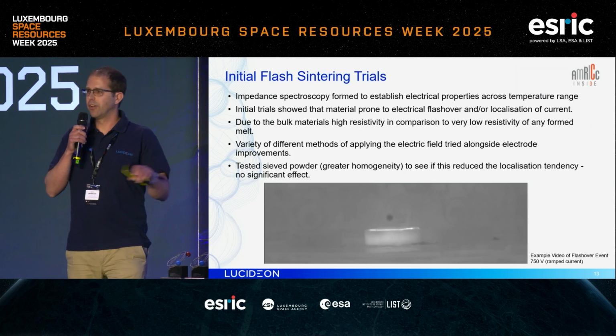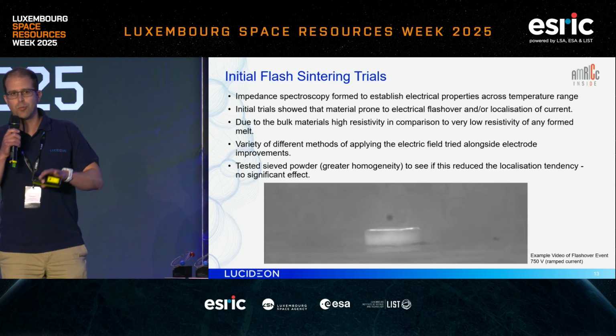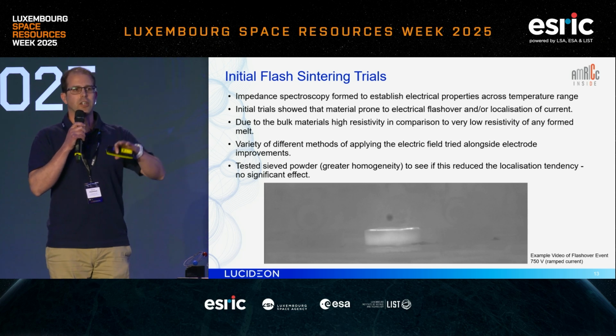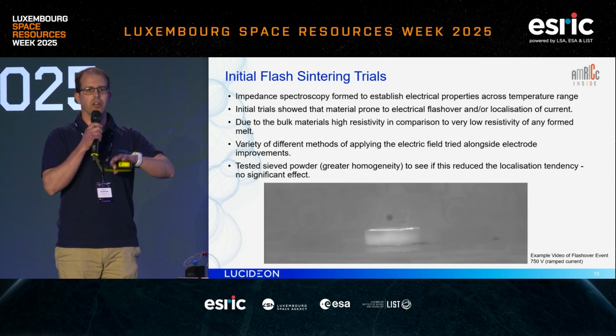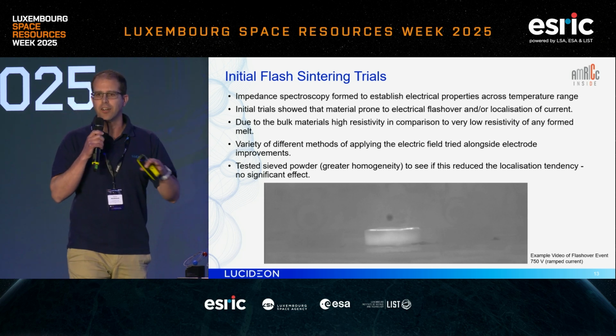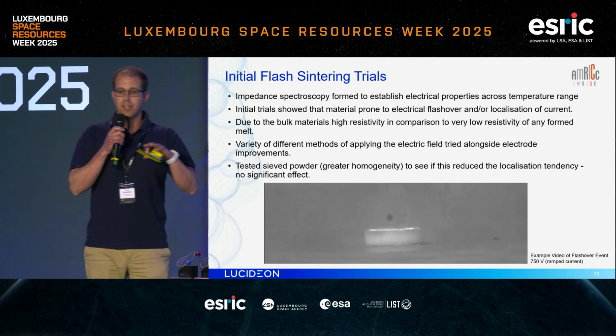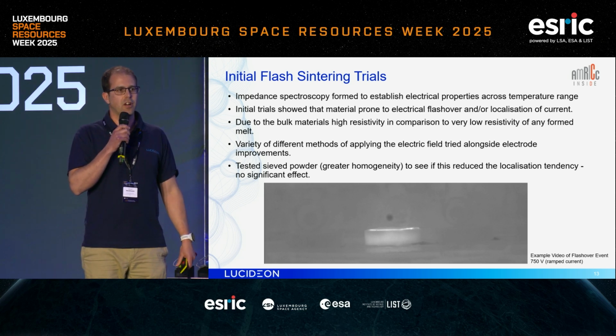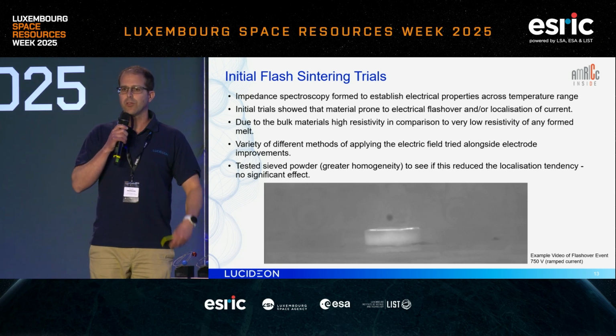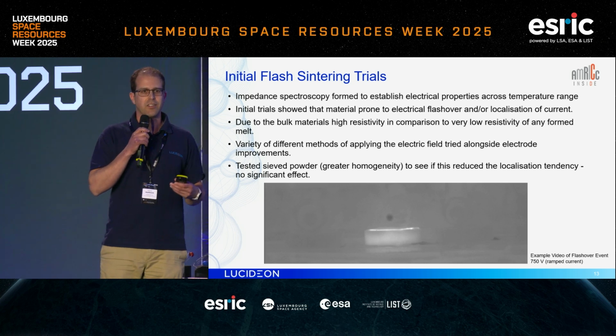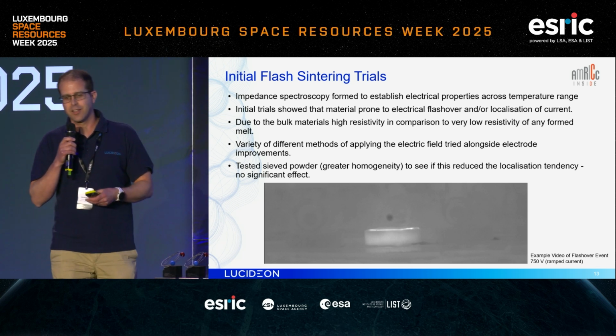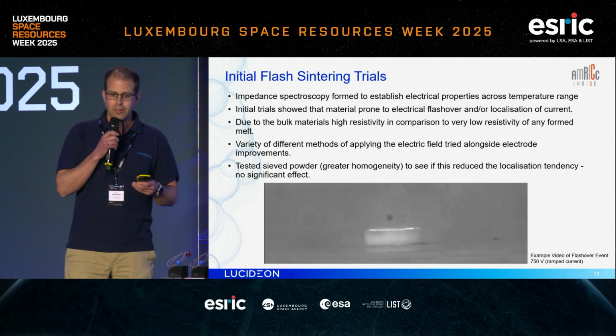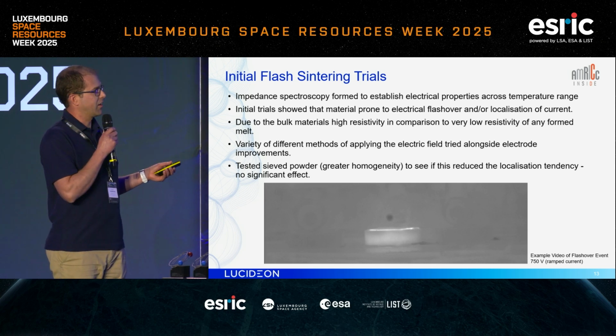Okay, so first thing we do in any kind of flash sintering project is apply some impedance spectroscopy to look at the electrical behavior of the material over a range of temperatures and try and get an idea. So regolith, in this particular simulant, starts off very resistive, and then as we apply these fields, we can start to ignite conductive pathways, and indeed, what you're going to see here is that occurring.